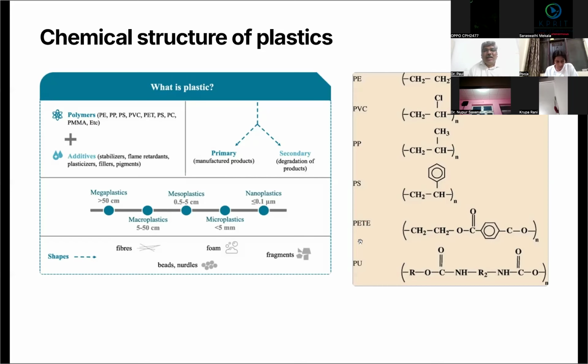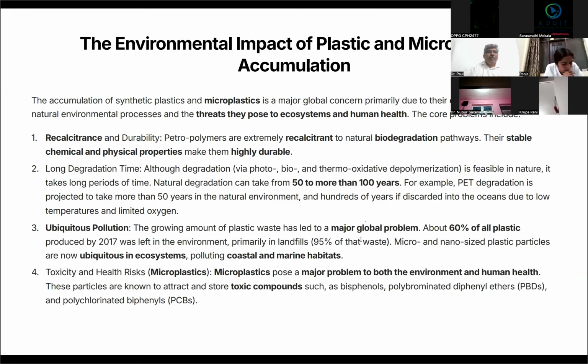So, what is the environmental impact because of this microplastic accumulation? These microplastics are very much recalcitrant and very hard to biodegrade in the environment, either in terrestrial or in aquatic systems. They have a very long half life. Usually, some of the plastics take even more than 600 years to degrade. Natural degradation can take up to 50 to 100 years for PET degradation, and it may take more if the temperatures are low and if the oxygen is limited.